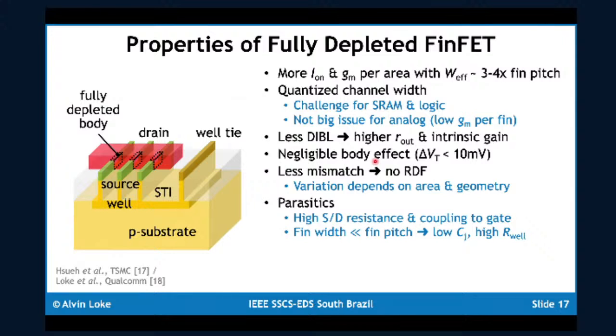There's substantially more parasitics given a much more compact three-dimensional structure, with nodes being much closer to each other. The source drain resistance is much worse because of spreading resistance to get into the fins, as well as the coupling to the gate. Because the fin width is much less than the fin pitch, the junction capacitances are low, which is not really significant because the parasitics are dominated elsewhere, but you have much higher well resistance, which has latch-up implications.